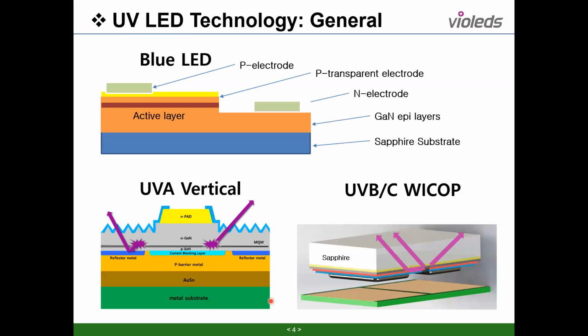So I made a simple schematic layer, which I explained in the bubble. So this is the general blue LED. From the bottom, this is the sapphire layer, the sapphire substrate. It's very crystallized and very transparent. We grow the gallium nitride crystal structure on the sapphire substrate.